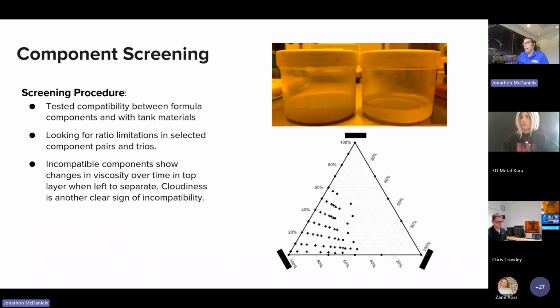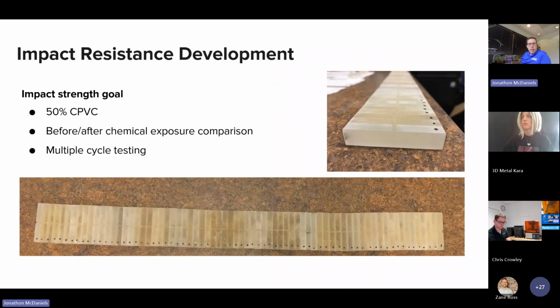One of the things we quickly learned during the development was that chemically tough and impact resistant materials really pushed the boundaries of what was possible with both photocurable polymers as well as the 3D printing equipment. So during the development, we needed to continuously run compatibility tests to ensure that the formula components would play well with each other, and also with the printer tank. Many good options had to be eliminated because they just didn't work as part of the whole formula, and others had ratio restrictions. Like I said, on the impact resistance, we're aiming for 50% CPVC before and after, and then multiple cycle testing.